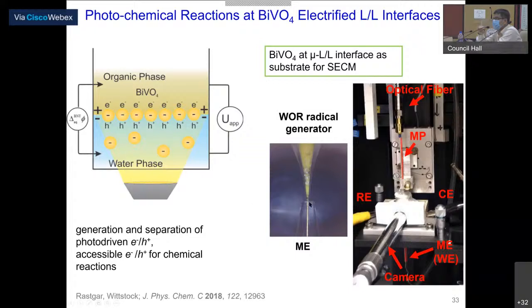So you blew it to a... here, yes, this one. Well, I think the particles stay in; they don't enter the organic phase. In this case, the aqueous phase is inside, so we get a rather clean surface. The material which is in the back doesn't play in that game. Here you have material that's a reservoir, but it doesn't play, and we can just refill it and generate a new surface. Okay.